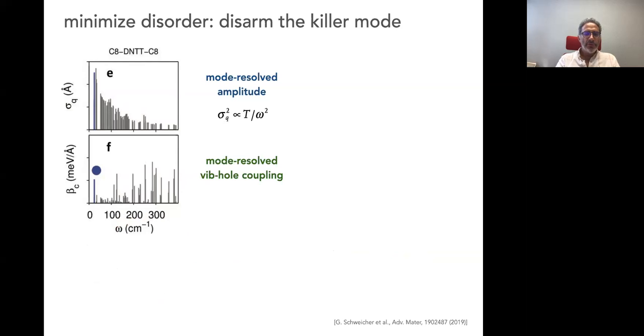So this is also what Henning was telling about. We've been working on trying to understand who is guilty of this disorder here. And here I'm putting an example for this functionalized DNTT. On the top panel here, you have just the amplitude of the fluctuations of the individual modes. So this is some mode-resolved study. And you see that basically the amplitude of the modes is going down with frequency. This is what is expected for harmonic oscillators. There's not much room for improvement here.